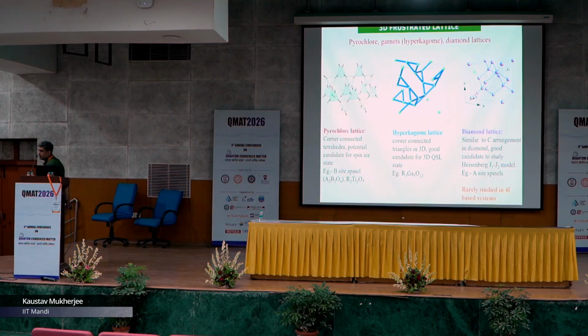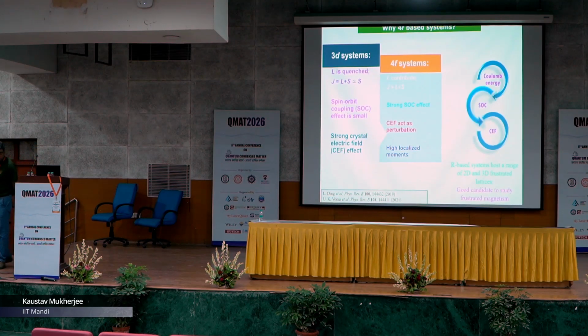Now, why did I mention the term rare earth? To see this, we just have to recall the origin of magnetism in 3d systems and in 4f systems. Basically, in 3d systems, the orbital angular momentum is quenched due to the strong crystal electric field effect. So the total angular momentum in this system arises mainly from the spin angular momentum. And also in 3d systems, the effect of spin-orbit coupling is very small.